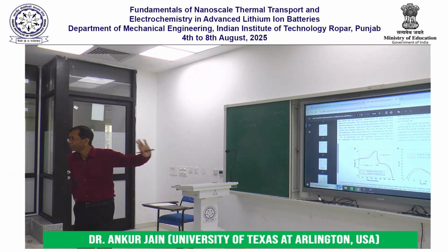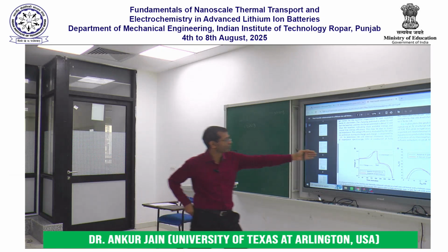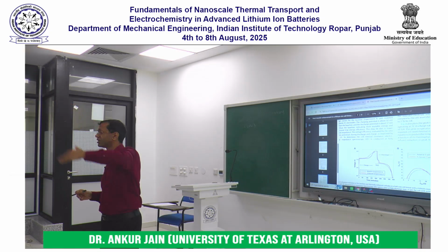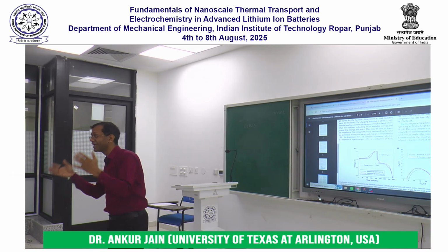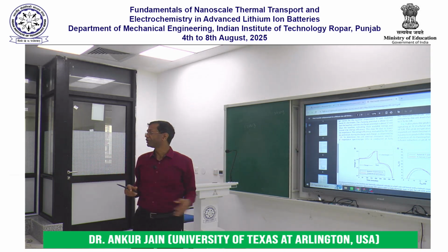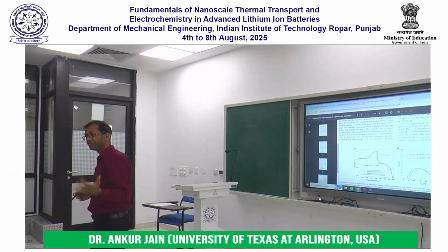Okay, this does not prove by any means that the aminosilane molecule will absolutely not disrupt the lithium ion transport, especially over a large number of cycles. We do not know. I mean, these experiments were only done for about 10 cycles. In reality, a lithium ion cell is expected to charge and discharge thousands of times. We do not know if that aminosilane molecule will survive, stay there for that long, and therefore we do not know what the effect of the aminosilane molecule will be on the long term thermal and electrochemical performance of the cell.